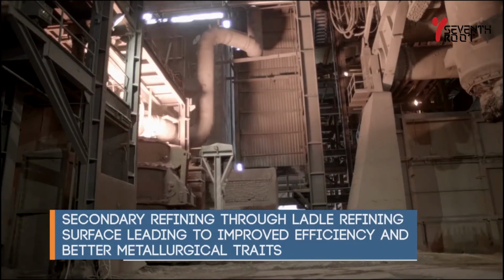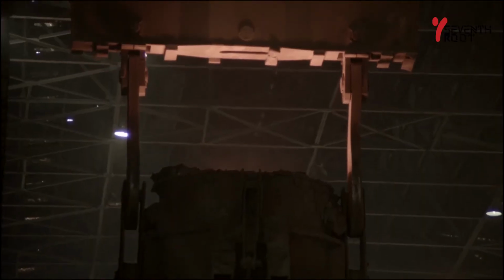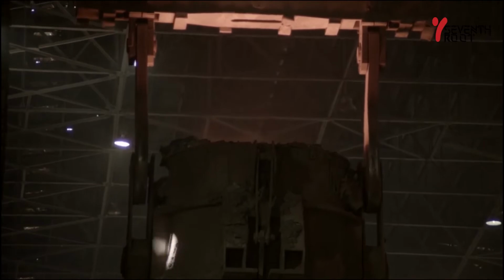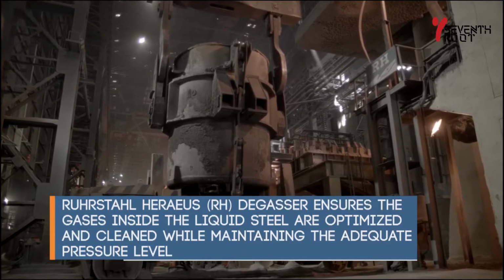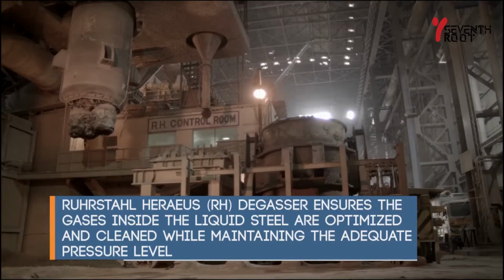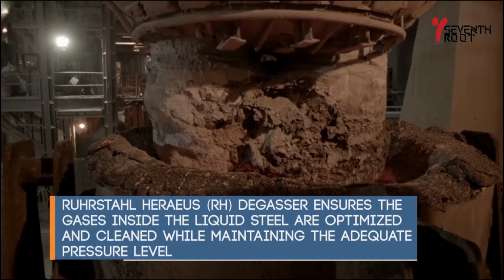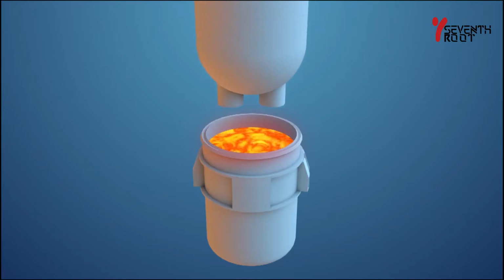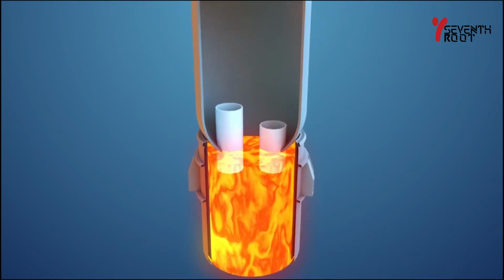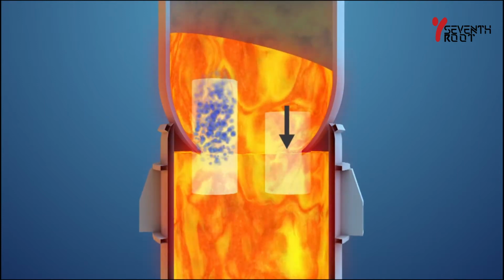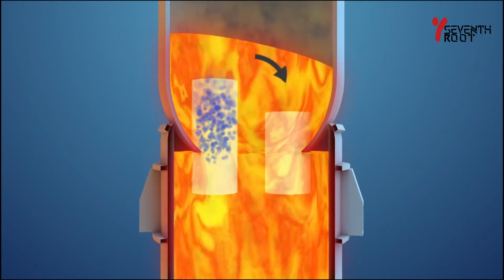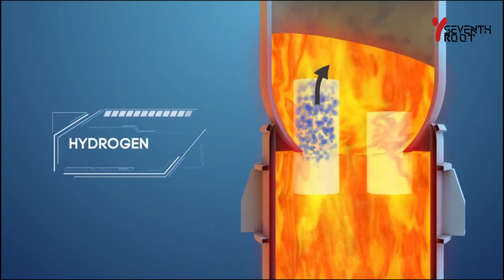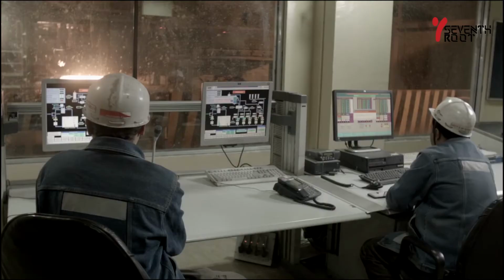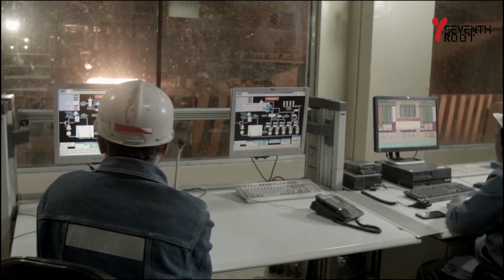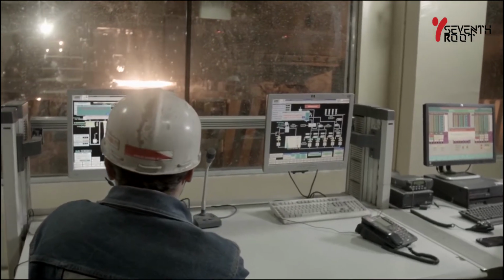and superior metallurgical traits. Gases dissolved in steel may have high detrimental effects like shatter cracks during usage and must be controlled in very close limits. At JSPL, Ruhrstahl Heraeus (RH) degasser is used for cleaning steel from dissolved gases like hydrogen, oxygen and nitrogen. In RH degassing, pressure inside the liquid steel is reduced to less than 1 mbar, while ensuring that the hydrogen content is less than 1.6 ppm, as specified in IRS T12-2009 rail specifications.